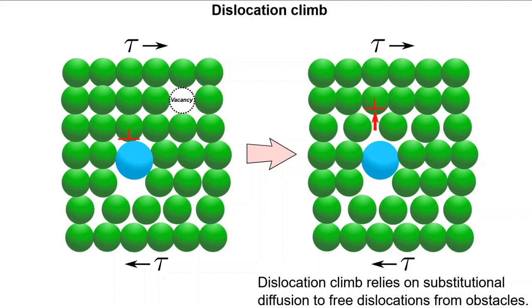Here I'm showing an edge dislocation that is effectively pinned from moving in the standard way by a substitutional alloying atom. At room temperature, this dislocation could not move, regardless of there being a vacancy nearby. At elevated temperatures, the vacancy, or an atom, depending on how you look at it, is free to move to the immediacy of the pinning atom. The result is that this will enable the dislocation to climb away from the solid solution atom. The result of which is that the dislocation now requires less shear to move, as it is free of the effects of the pinning atom. Now imagine this going on a few trillion times, and we have a complete picture as to how large-scale deformation can occur at temperature with relatively low loads.